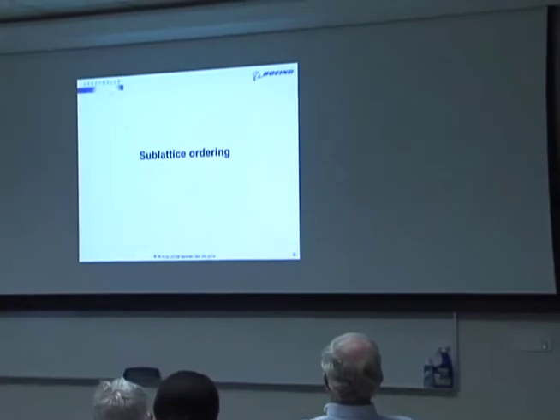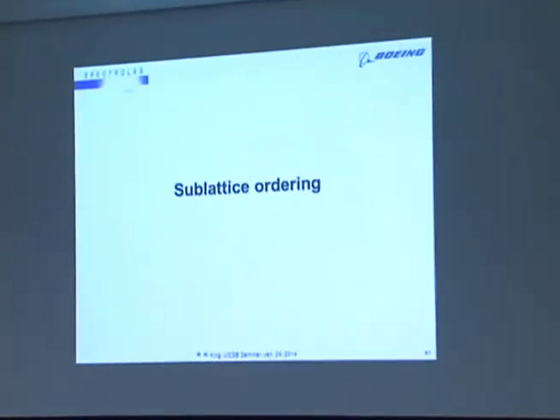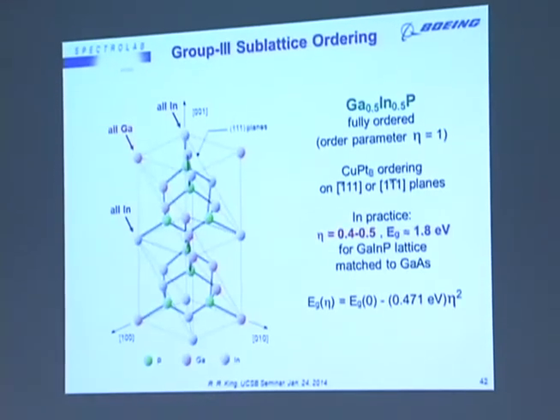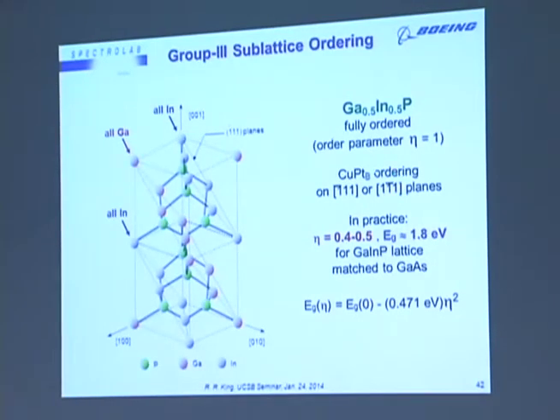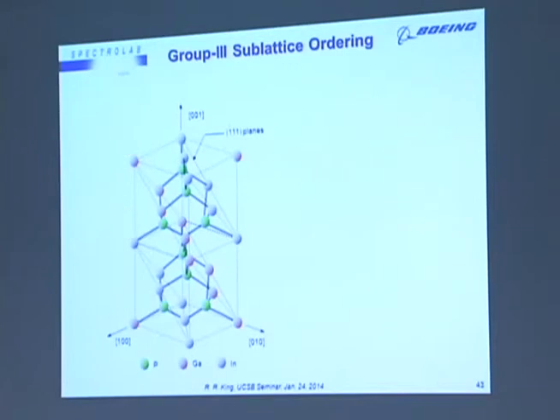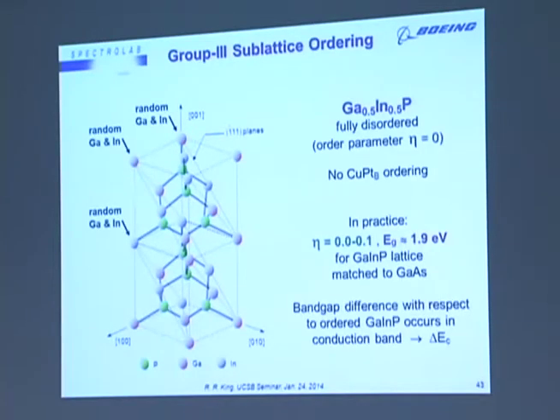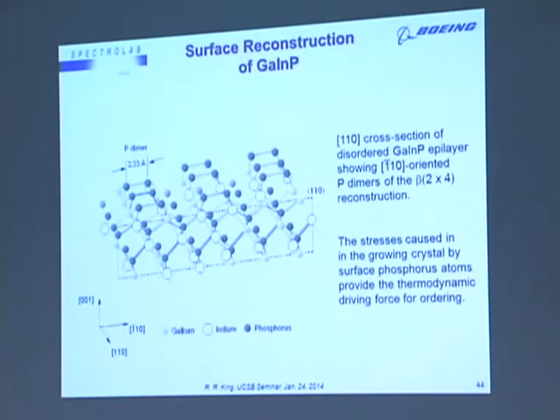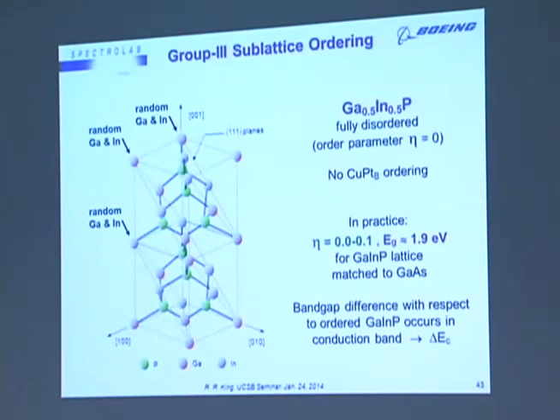But I'd like to just talk for a moment about sublattice ordering also, because that's another important way to control the band gap of the wider band gap gallium indium phosphide materials that are used in multijunction cells. So in fully ordered gallium indium phosphide, we have 111 planes that either have all indium or all gallium, as you see in this crystal structure. If you look at these atomic components of the 111 planes for a moment, in fully disordered gallium indium phosphide, you can see now that those 111 planes have a random combination of gallium and indium on each of the 111 planes. So the composition of the gallium indium phosphide is the same, but the band gap can shift as a result of this disordering on the group 3 sublattice on these 111 planes.